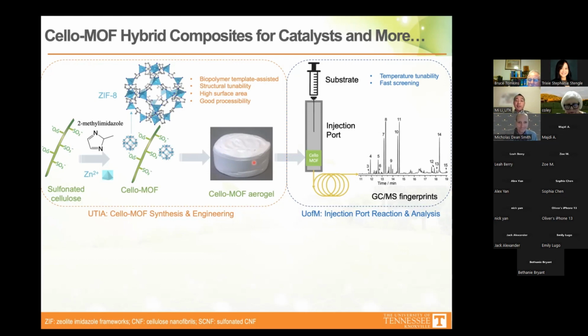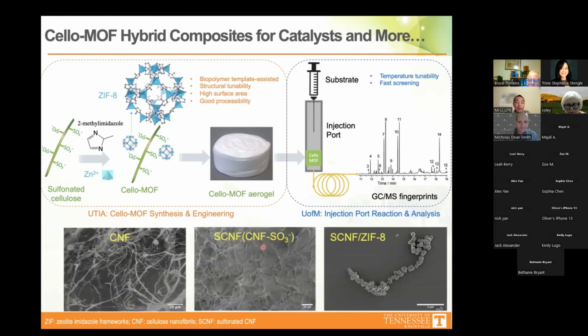From the processability standpoint. Okay, so we made some tests, and again, this is a cellulose nanofibril. It's about 100 micron in length, and then we modify the nanocellulose to introduce the negative charge on the surface, and then we grow the MOF on this cellulose fiber. On the bottom right here, a beautiful picture shows that the MOF are the dots right here, and they are well dispersed along the nanocellulose fiber. So that means this method works.